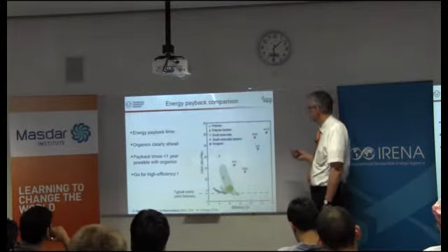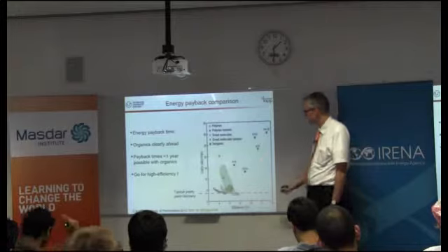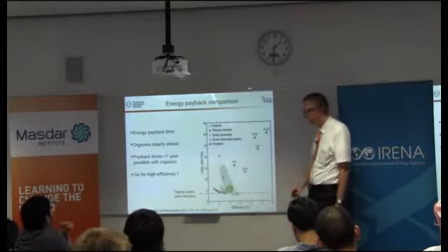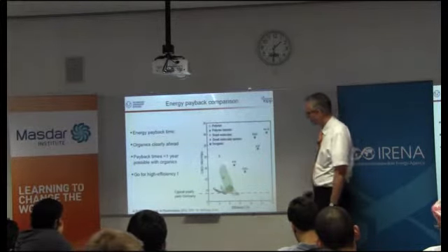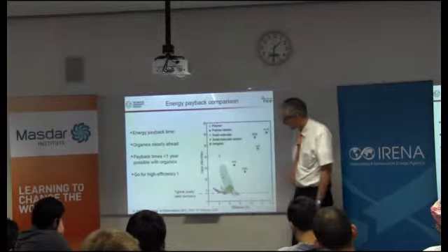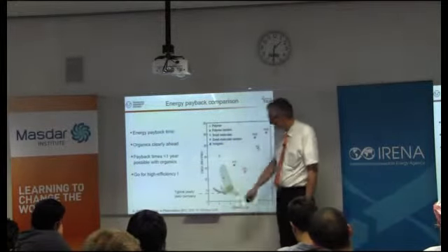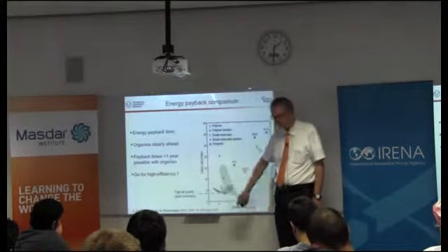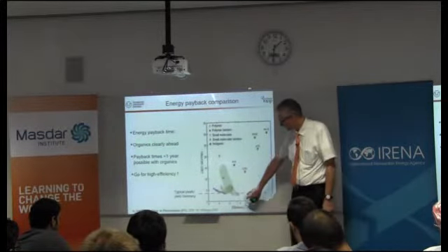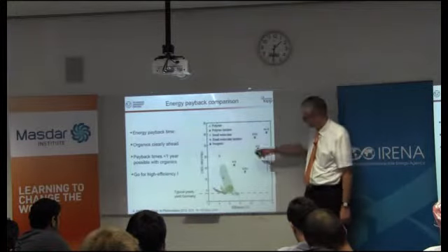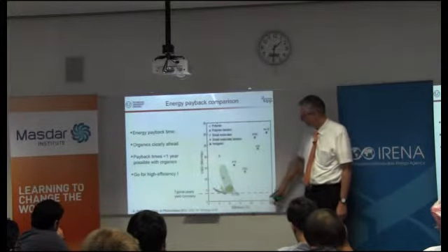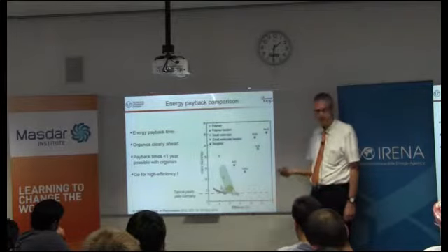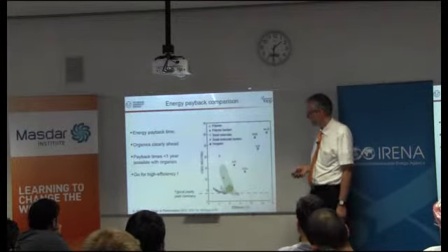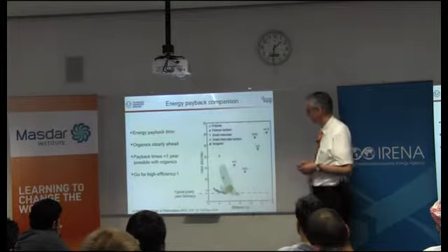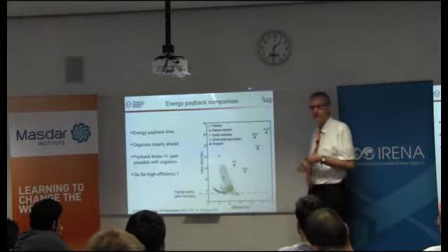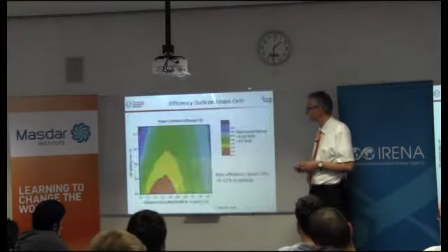But the basic message is that most inorganic PV systems, at least in Germany, still have several years of energy payback time. Whereas organics, these curves are organics. If you are in a range of, say, 5% or so, it's already in Germany only 1 year. But if you go, say, to 10, 15, or even 20%, this curve goes 1 over x. You can get energy payback times even in Germany, which are 2 months or so. So the potential for a very short energy payback is there. Again, it depends on the efficiency.